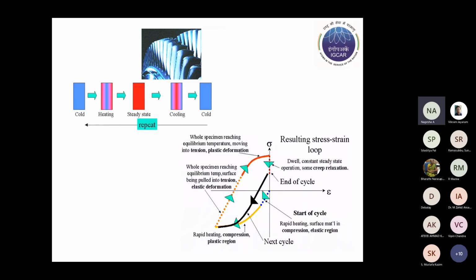So at the outset, I just want to give a brief background about the high temperature low cycle fatigue testing. This shows the situation when we are in the process of starting up. This is a high temperature component. Typically, you can say it's a turbine blade. At the starting time it's cold, so when the component is getting heated, the surface expands fast, but it is getting restrained by the interior, by the bulk. So what happens is we have a compressive stress being built into the component, because the thermal expansion gets restrained by the colder bulk.